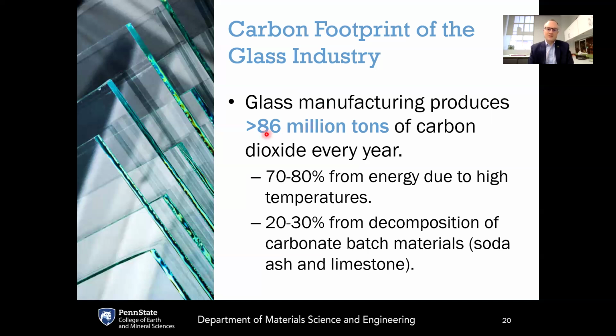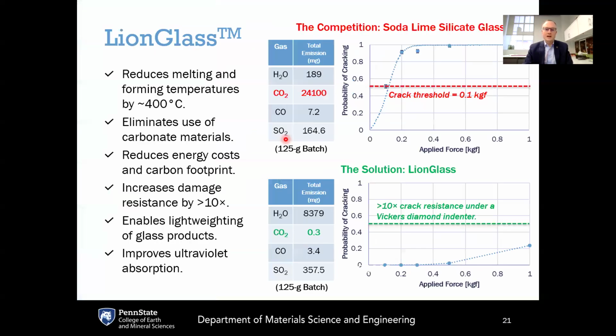And what we're trying to address is the fact that the glass industry produces over 86 million tons of carbon dioxide every year. About 70 to 80% of that is energy consumption due to the high temperatures required for melting, about 1450 degrees C for soda lime. And the other 20 to 30% comes from decomposition of carbonate batch materials. So soda ash and limestone are both carbonates, and when they're melted, they decompose to oxides, releasing CO2 in the process. This latter part here could be addressed by recycling of glass, but that still doesn't help when it comes to energy consumption. So we really need to do something to eliminate the use of carbonate batch materials and significantly lower the melting temperatures if we want to have a big impact on this number.